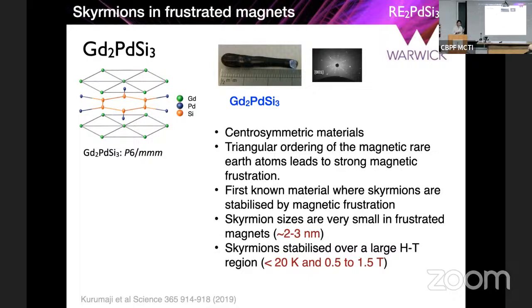is proposed to be only of the order of 2 to 3 nanometers. The ones that I showed you earlier, like the manganese silicide and the copper oxyselenate, the very well-studied examples I listed in the very beginning of the talk, there the skyrmion sizes are about 60 nanometers or 50 nanometers. So this is very, very small.